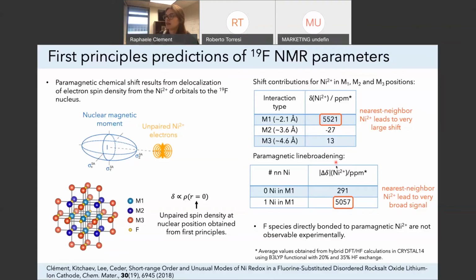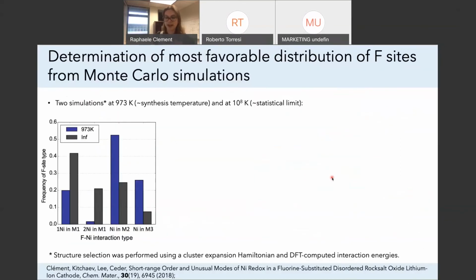And so what this really tells us is that what we are seeing experimentally is likely not coming from fluorine that are directly bonded to nickel, because these signals are too broad. So this already gives us information about what we can learn with NMR spectroscopy on these materials. But this is not the complete picture here. We also need to know the most favorable distribution of fluorine sites in these materials from Monte Carlo simulations.